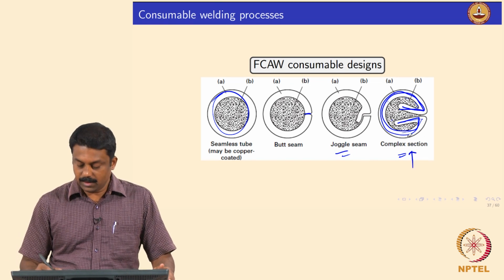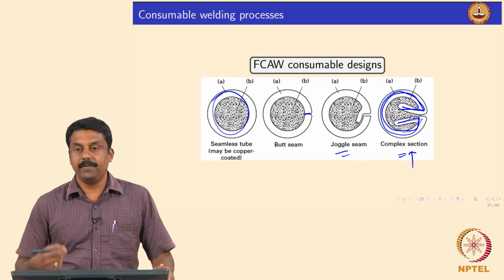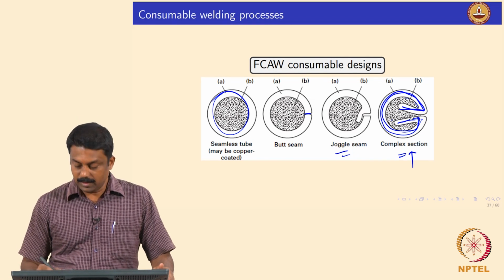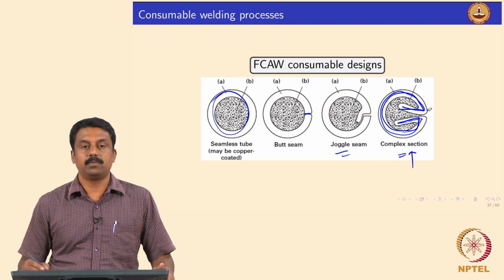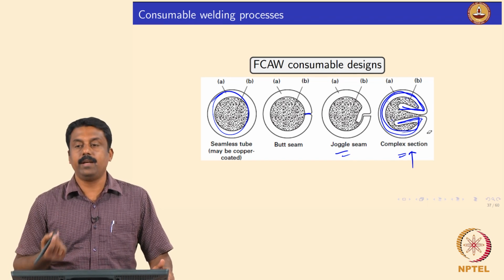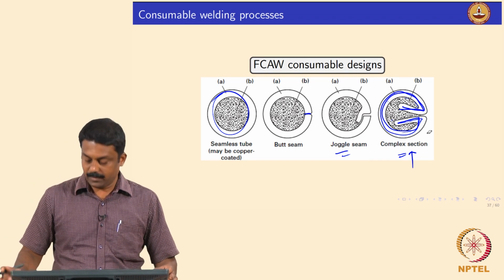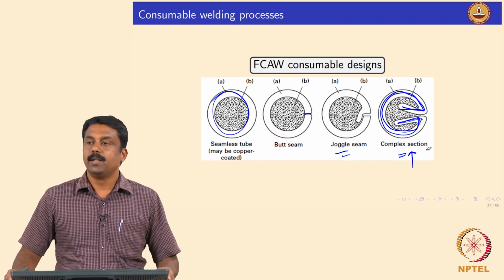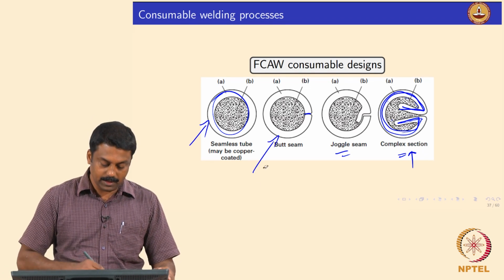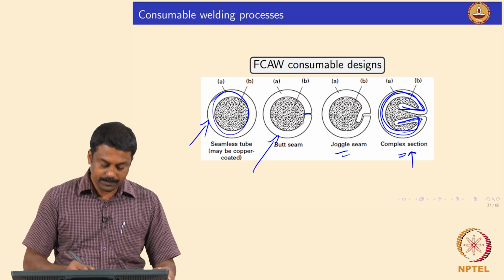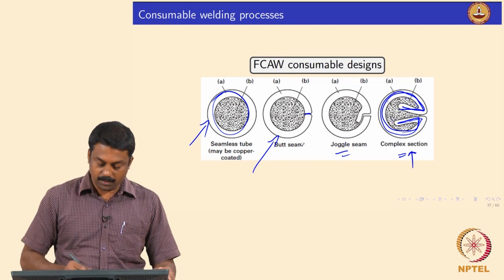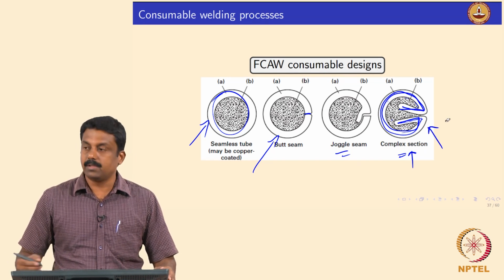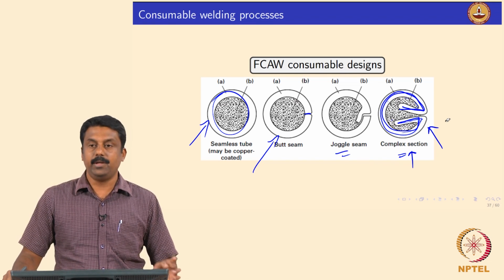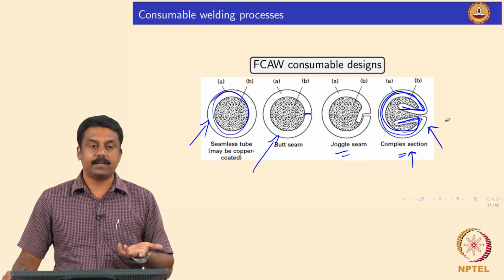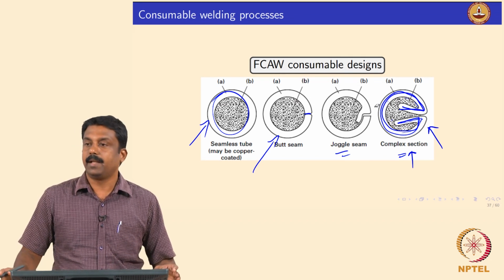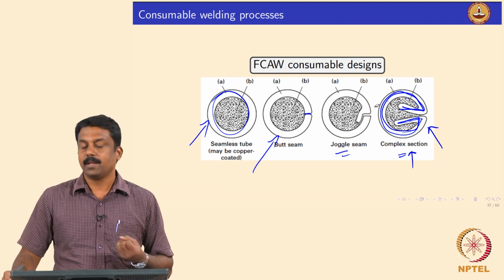So, in these kinds of electrodes, the amount of flux which is there is not sufficient to produce enough shielding. Okay. Because here the metal volume is much higher than the flux volume. So, such a complex section geometry is used in conjunction with the shielding gas. Okay. In most of the cases, self shielded FCAW would have a design of a seamless tube or a butt seamed electrode. So, for a complex section or joggle seam sectioned FCW consumable, generally you need to have an extra shielding, because the volume fraction of flux with respect to the metal decreases significantly. So, you need to generate more gas. So, you may have to use an external shielding.